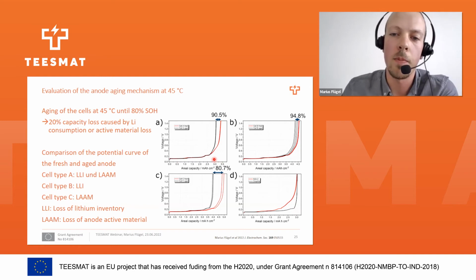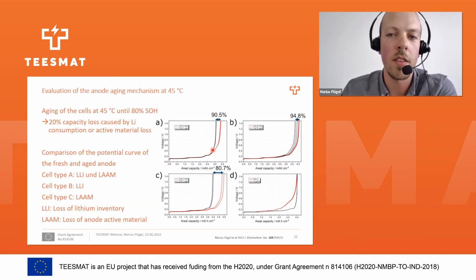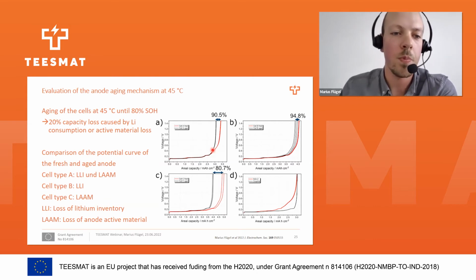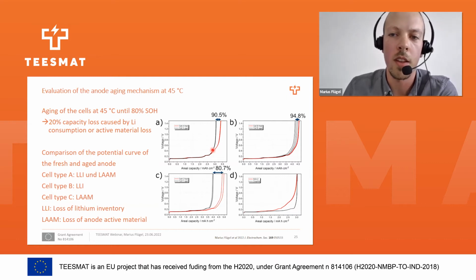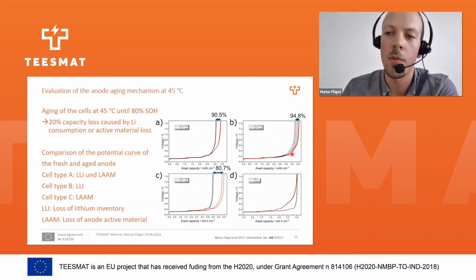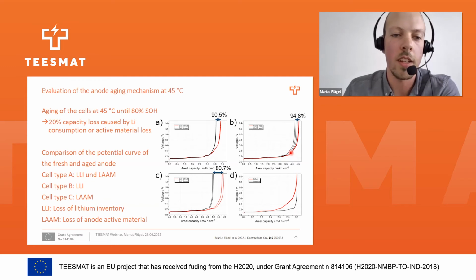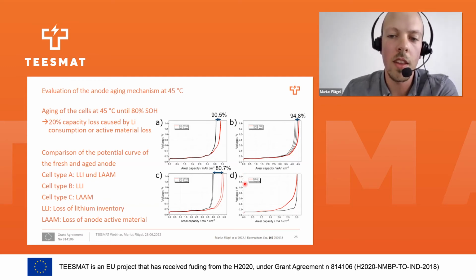Knowing this, we can see that for cell type A, we saw the 10% capacity loss, which was mainly caused by the loss of active material, mostly the loss of active silicon. However, we lost 20% of capacity. So for cell type A, we saw capacity loss caused by loss of lithium inventory as well as loss of active material. For cell type B, we hardly saw any capacity loss from the active material, only 5%. So the main capacity loss has to be due to loss of active lithium. For cell type C, we saw that lithium was hardly active anymore. So most of the capacity loss was due to loss of active material.